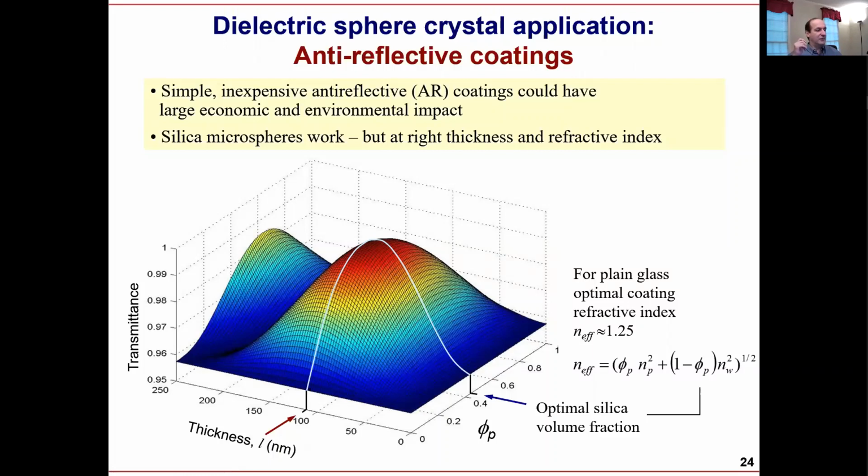If you take a regular glass surface, glass reflects about 4% of the light from one surface. So in any glass, if you let light go through, you're going to lose, as transparent as it seems, 8% of the light. 4% on one surface of the glass, 4% on the other surface. So 8% of the light is always going to be reflected regardless, right? There is no completely transparent glass.